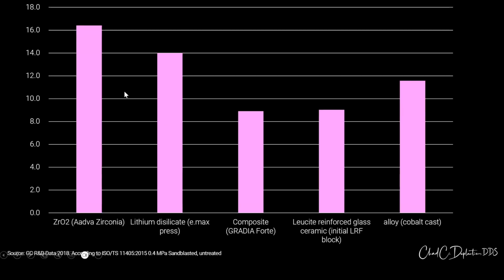When we look at an independent study from GC that shows us the tensile bond strength of GC Fuji Evolve, you can see that it performs well. Once again, I'm not going to say great, but I would say that it performs almost best to zirconia. It also performs well when we look at it compared to lithium disilicate, composite restorations, leucite reinforced restorations, and alloy. So this is a wonderful cement.